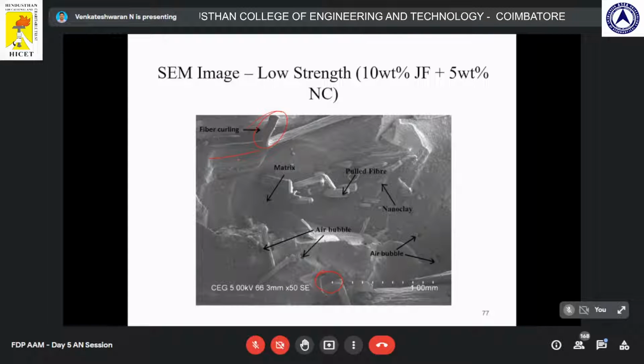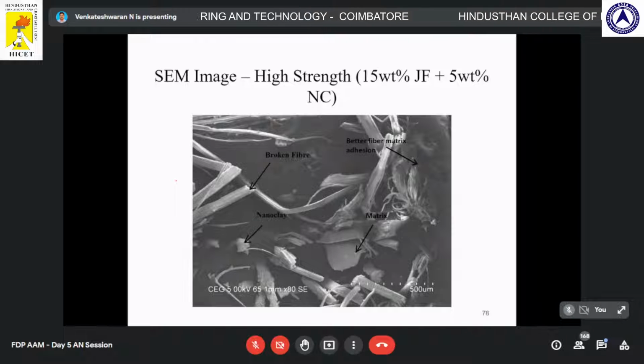So the strengths are low. Here, if you have seen, even after it breaks, the adhesion is very good. The adhesion between the fiber and the matrix is very good, so that I am getting the best properties at 15 weight percentage. Even the fibers have bent without failure. Not all the fibers have failed.